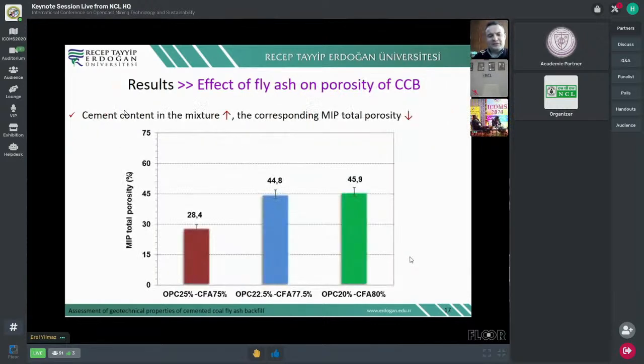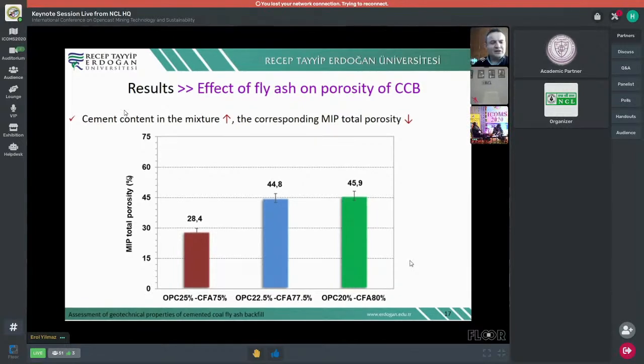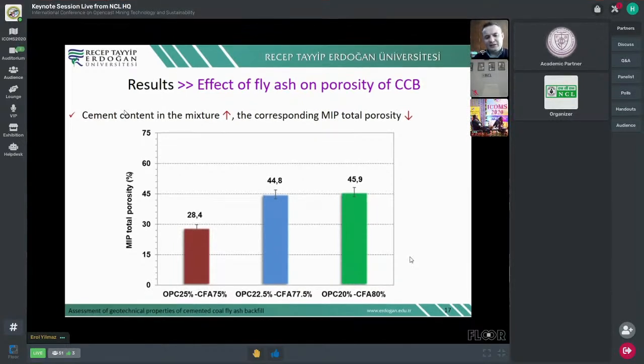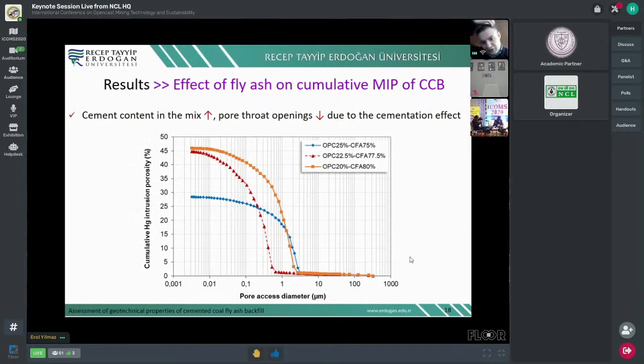Here also the proof of what I said in the previous slide. Effect of fly ash on porosity of the backfill. Of course, when you increase the cement content, which means 20 to 25%, you will see the total porosity significantly decrease to 28%, which will create a higher strength value.